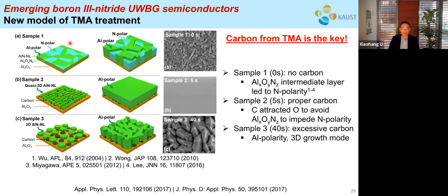And for a sample without any carbon, we will have this blue color nitrogen polar aluminum oxide nitride. And if you grow on top of it, you will have this very rough nitrogen polar aluminum nitride surface, which is not good for device applications. And for the second sample with a proper amount of carbon, right, with scattered carbon, those carbon can attract oxygen from the sapphire to avoid the formation of aluminum oxide nitride, to impede the formation of nitrogen polarity. And for the third sample with excessive carbon, those excessive carbon will serve as a mask. And if you grow on top of a mask, you will have those irregular faceted aluminum nitride on the surface, which is also not ideal for device application. So a proper amount of carbon from the trimethyl aluminum is the key here.